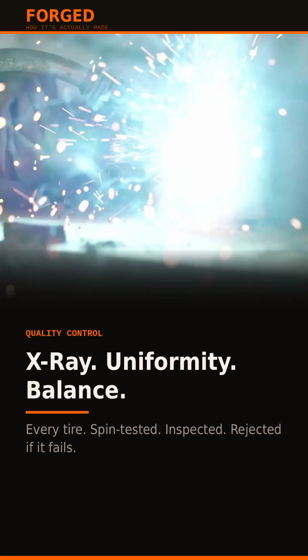After molding, the tire goes through quality control that would surprise most people. Uniformity testing mounts each tire on a precision machine that rotates it at speed and measures force variation around the circumference. Any imbalance in mass distribution or stiffness is detected and flagged. X-ray inspection checks for internal structural defects invisible from the outside. Steel cord separations, voids, contaminants. Tires that fail any test are destroyed. The rejection rate at high-quality tire plants is typically under 1%, but the testing is comprehensive on every single unit.